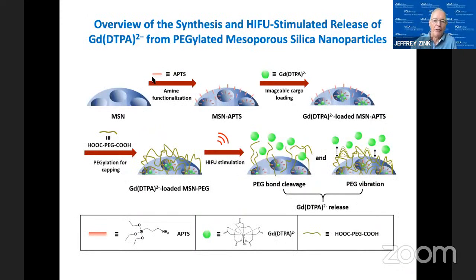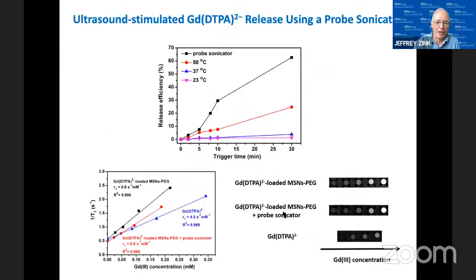We need to have now an ultrasound responsive cap. And the simplest one that we use is a PEG cap, a biocompatible polymer. In this particular case, we were able to show, as we and others have done, that ultrasound can actually break apart the polymer. So we showed that the polymer is intact as a capping agent. In the presence of ultrasound, the cap breaks apart, and HIFU stimulation breaks it apart, and we can release the drug. So that's our very simple capping system for this particular experiment.